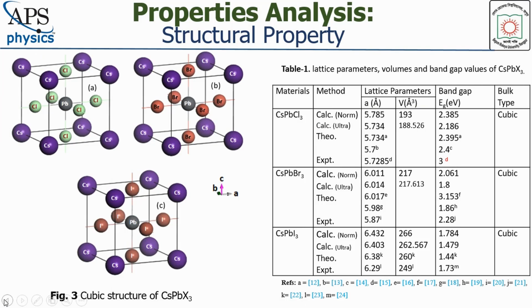Cubic structures of cesium-lead chloride, bromide, and iodide are depicted in figures A, B, C respectively, where halides are face-centered atoms, lead takes the position of the body-centered atom, and cesium is the corner atom of the cubic unit cell. Table 1 shows the collection of some values regarding lattice parameters, volume, and band gap of the perovskites. As we have chosen cesium lead chloride first and decided to replace the halogen for tuning the properties, both norm conserving and ultra-soft pseudopotential methods are implemented to get a reliable result.